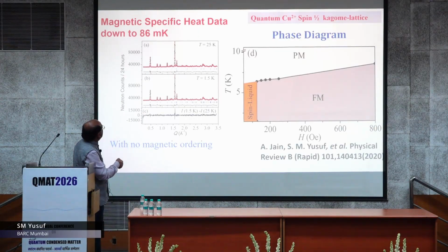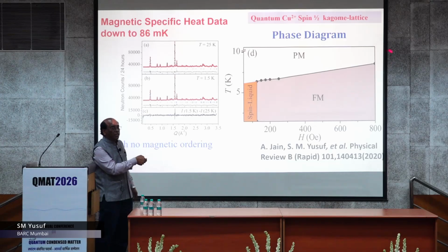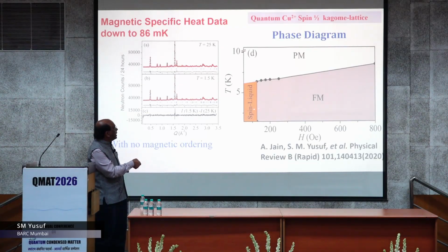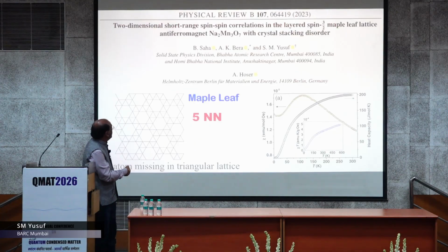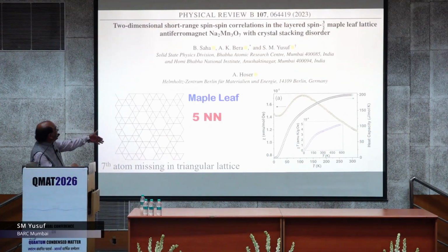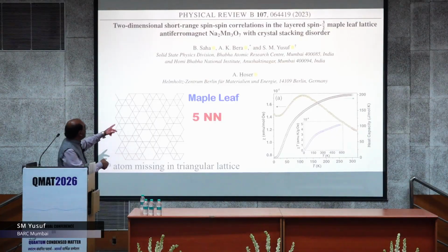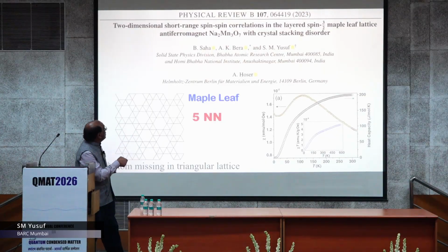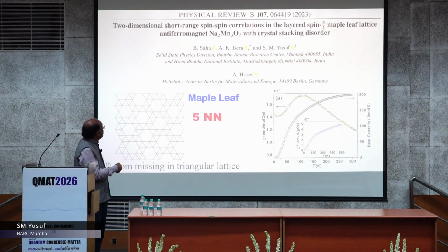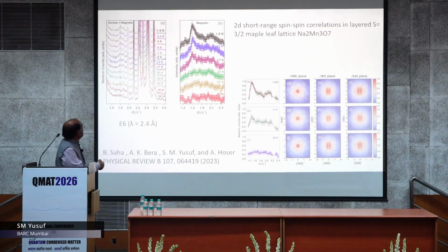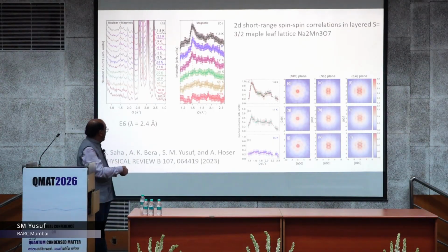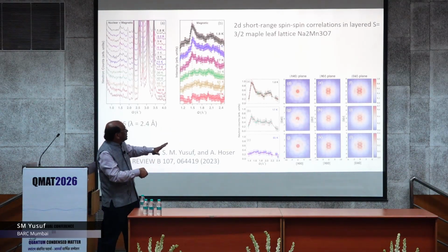So this is the neutron diffraction, which confirms that there is no magnetic ordering. This is the phase diagram. This is the spin liquid under magnetic field. We do see this transition from spin liquid to ferromagnetic in this system. If we go to yet another example, the maple leaf lattice, that is again playing with the triangles. In this case, which we worked on recently, Anup Bera is here, and in this case again we see that magnetic short range correlation much above the so-called ordering temperature, and this is the 2D plot of how this diffuse magnetic scattering is there.